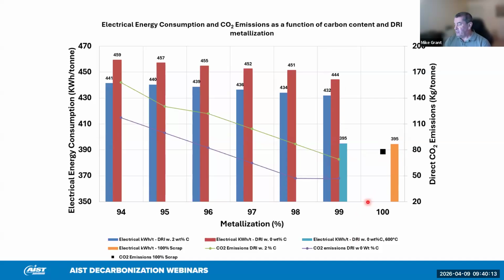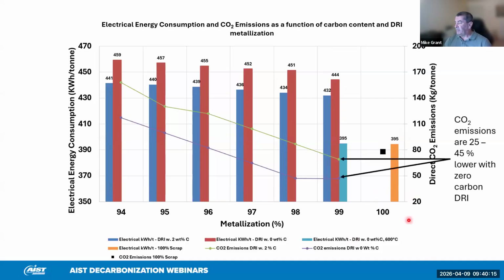And if we look at the CO2 emissions, because we're charging less carbon in the process, we are producing less CO2, around 25 to 45% lower CO2 emissions when we charge zero carbon DRI. So there's that benefit alone, despite the fact that you're consuming a little bit more energy and you don't have carbon in your process.